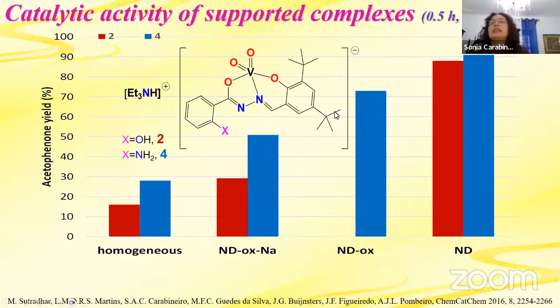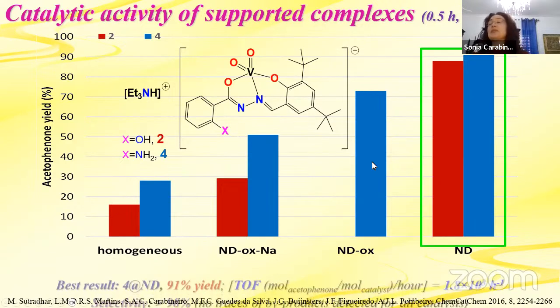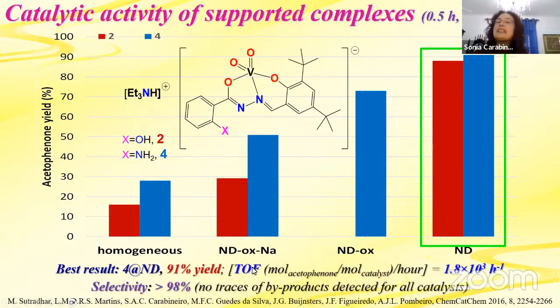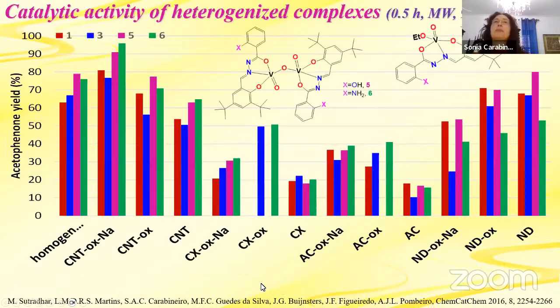Complexes 2 and 4, the ones with OH and NH2, could only be supported on nanodiamonds. It was interesting. The best result was obtained on non-functionalized nanodiamonds, because if we functionalize them, the result is worse, but of course it is better than the homogeneous one. So the best result was this complex with 91%, and again, very good selectivity.